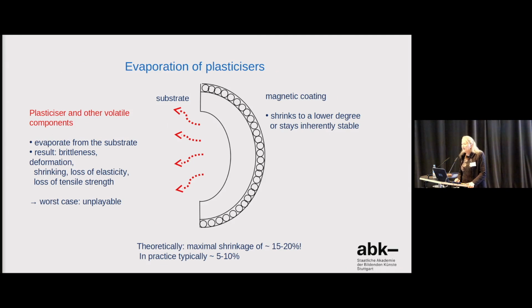So what happens if the plasticizers evaporate from the substrate? The result is brittleness, deformation, shrinking, loss of elasticity, loss of tensile strength, and in the worst case the tape becomes unplayable, and the shrinkage is always towards the layer where most of the plasticizer can evaporate. So the magnetic coating shrinks to a lower degree and stays inherently stable, and this is the reason why it keeps the longer way while the substrate is shrinking and the material is deforming.